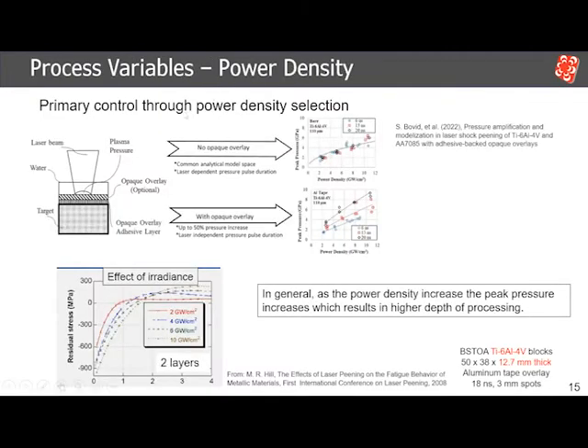A lot of the research historically, and even the recent ones by Stan, has shown that the power density is directly linked to that peak pressure, meaning the higher the power density that you're using, the higher the depth of residual stresses that you're achieving, and vice versa. So we have the ability to control the residual stress profile that we need in order to get the best processing.